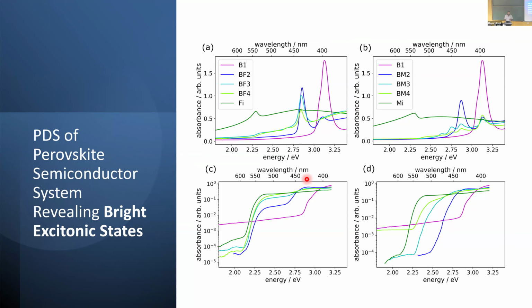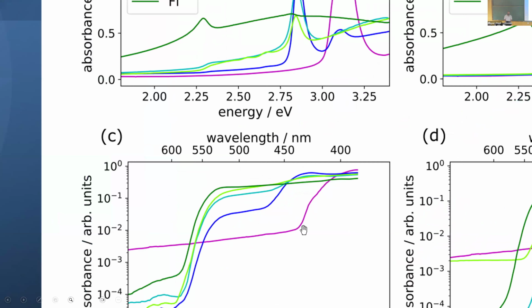Now if you compare the corresponding PDS spectra at the bottom, you notice a very unusual thing. Do you see a peak here in the purple sample? You don't see a peak. Why? You would argue that if absorption shows a peak there as a strong excitonic signal, and we're looking at only weak signals, such a strong signal should easily show up in PDS. But that doesn't happen, because in this class of perovskites it's very peculiar that these excitonic states are extremely emissive in nature. So the absorption that happens in these excitonic states emits a lot of light.